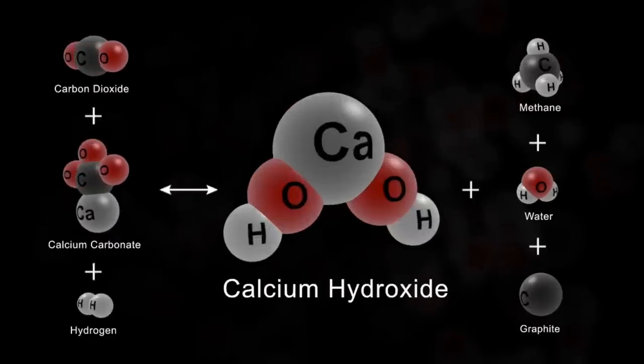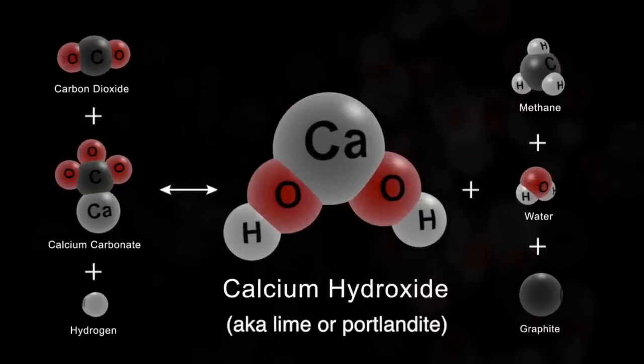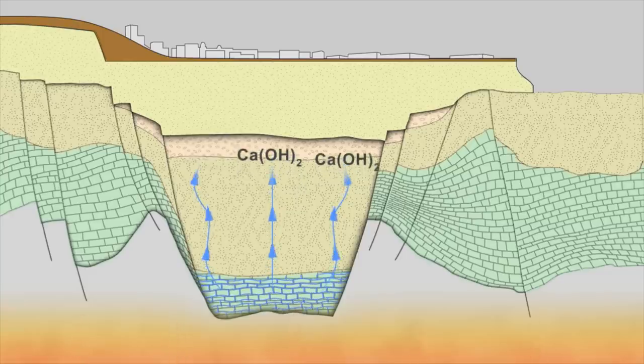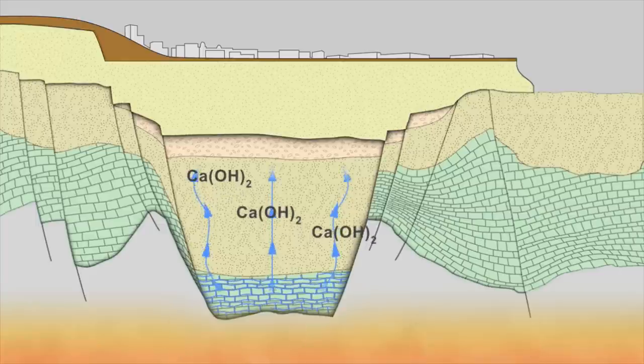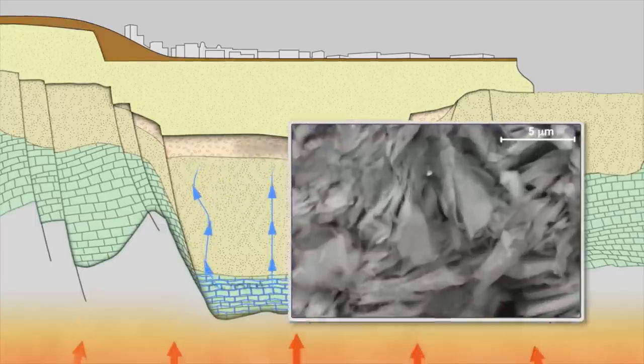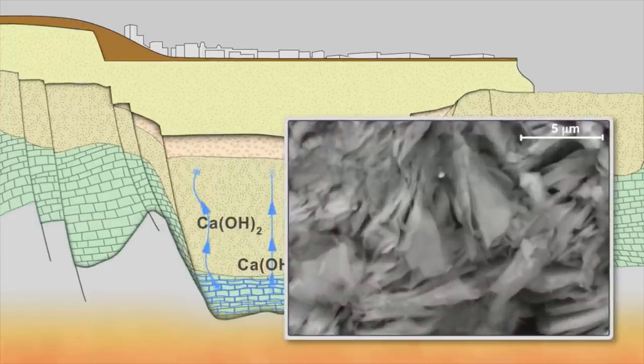CO2, but most importantly the lime. The lime that forms at depth then reacts with the pozzolana rich layer transforming that layer into concrete like rock.